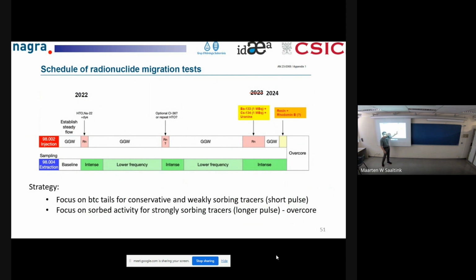I'll show you later. And then sometime later, we haven't done that yet, inject the pores with the strongly sorbing tracers. The idea is to stop right after injecting the tracers, and then overcore. You want to look at the tracers soaked in the rock rather than the tails, because then you will be able to see where it soaks, how it is related to the structure of the rock, and see the structure of the flow field in a way. And then you do different sampling frequencies depending on the part of your interest. But basically, that's the strategy for the first part, which we already did.